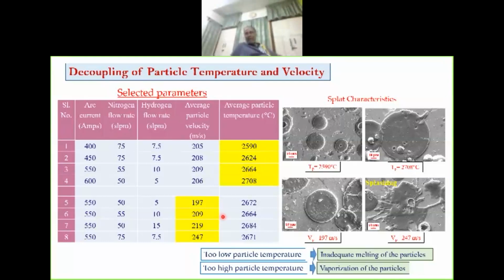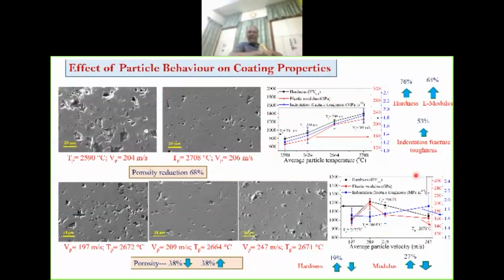Velocity, alumina particle 197 meter per second. See the shape of the splat? And you carry it to 247, see the splat, it is deformed. A high velocity will worsen the properties of the coating as it has been found. What happens when you spray with an increase in particle temperature? In this range of the experimentation, while the velocity was near constant, we could see that with improvement in particle temperature, we got improvement in properties like fracture toughness, elastic modulus, and hardness.